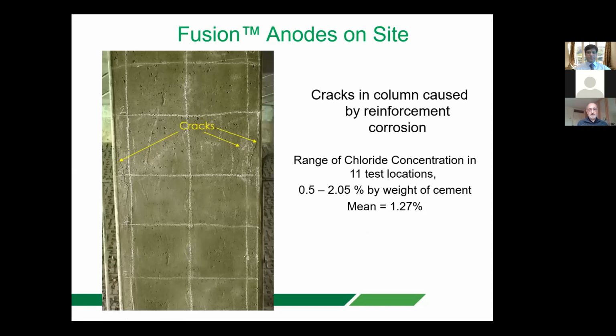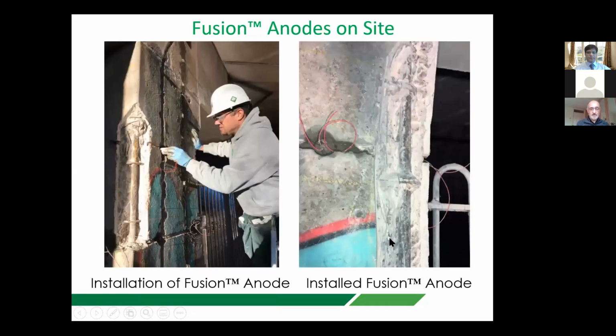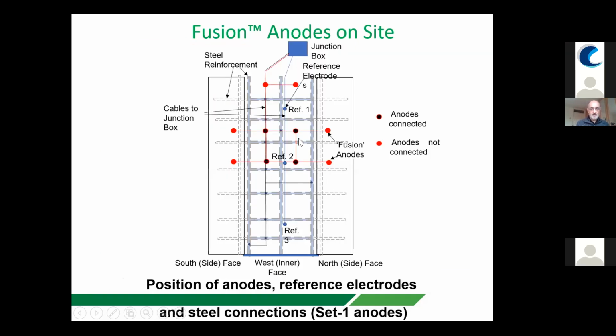And we had a chance to do this on a bridge structure, a column that corroded and forced some cracking of the concrete on the edges. Steel reinforcement is about here. The chloride level was up to about 2%, particularly at the regions where corrosion had occurred. So we saw this as an ideal opportunity to try the fusion anodes. Here's where we actually removed the concrete and reinstated the steel reinforcement, and we've applied galvanic anodes either side of this patch repairs on both sides of the column. Roughly, that was the sort of the layout of the galvanic anodes.